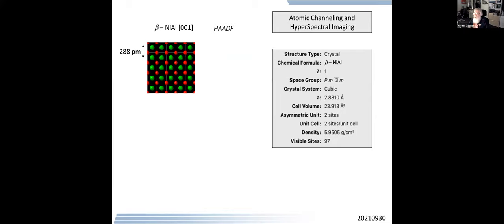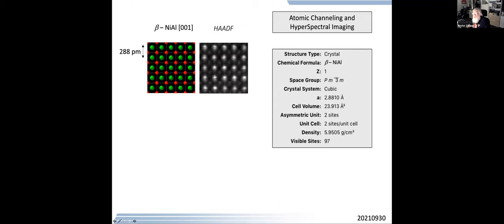Here's one of my favorite materials from back in the days when I was at U of I, and the sample's actually a part of a single crystal that Hamish gave me years ago. I never throw anything away, and I still have some of these samples. This is beta nickel aluminum. If we look down the 001 axis, we can see an ordered array of nickel and aluminum atoms. We can do an HAADF image of it.